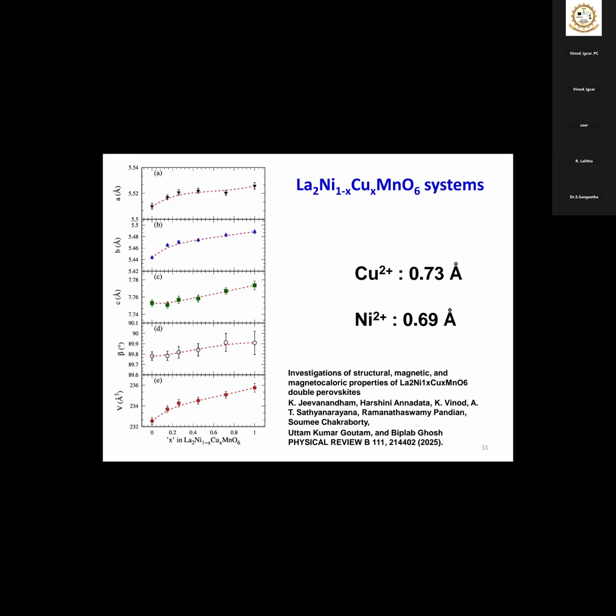Okay, now the next part is copper doping. Here the magnetocaloric part, I will not go into detail, but the magnetic part I will just cover. See, here the thing is nickel is 2 plus. Nickel is atomic number 28 and copper is nearby, 29, with a slightly higher radius. Copper is slightly larger in that octahedral site. So this is the result.